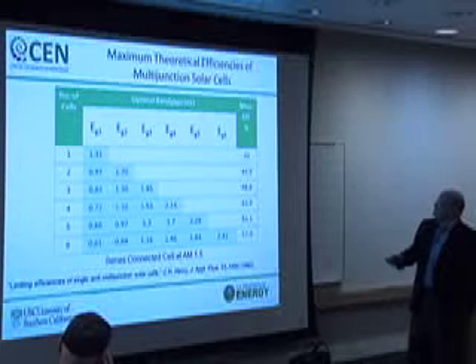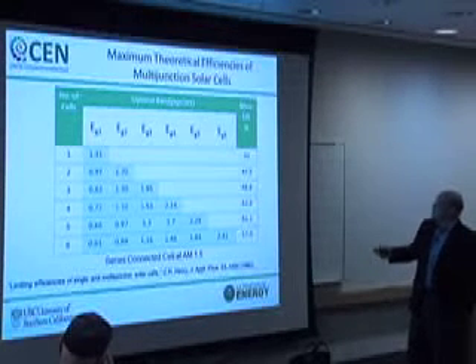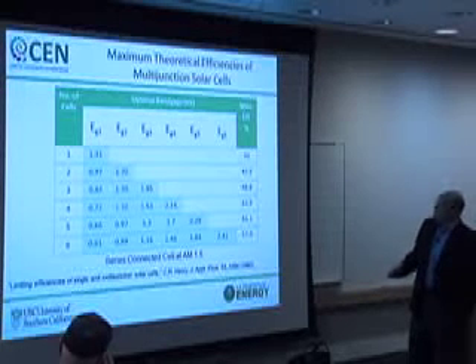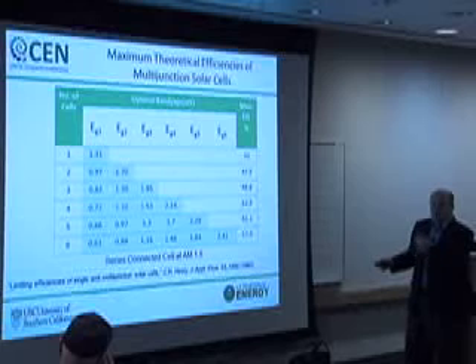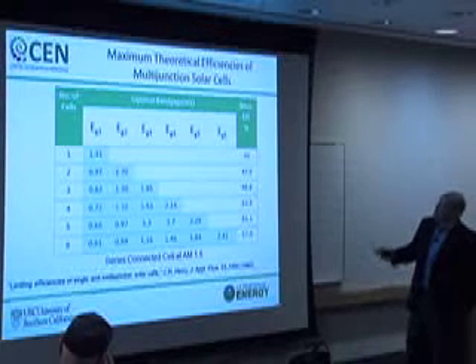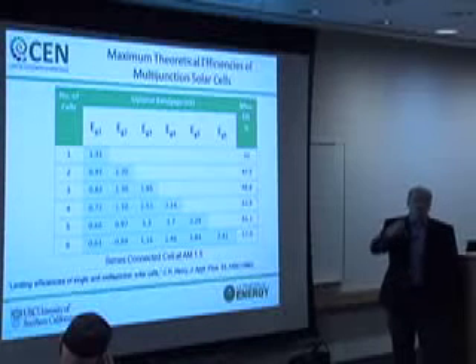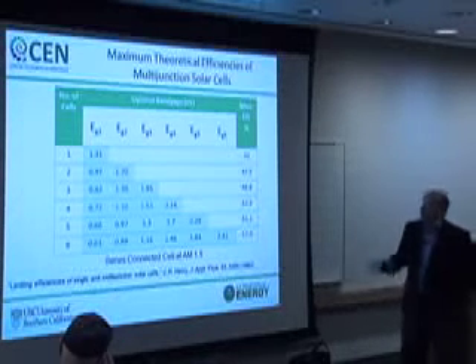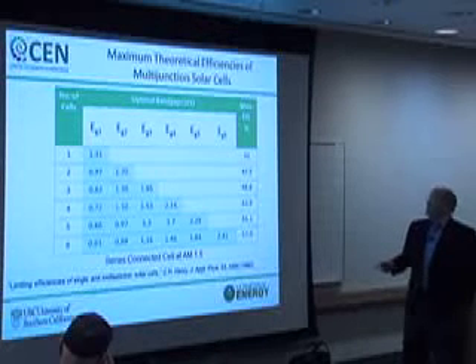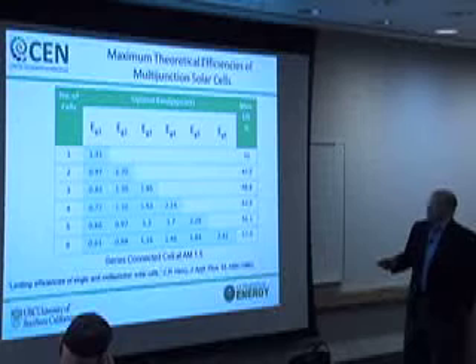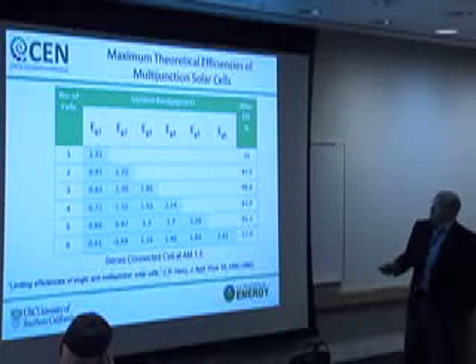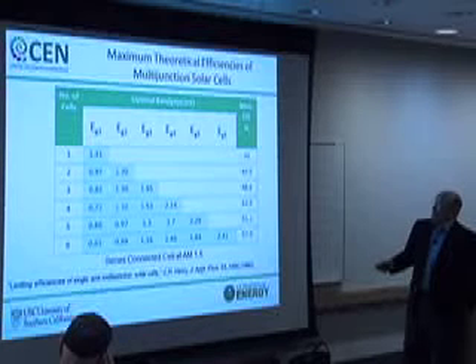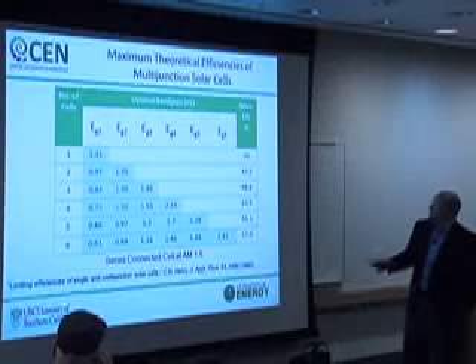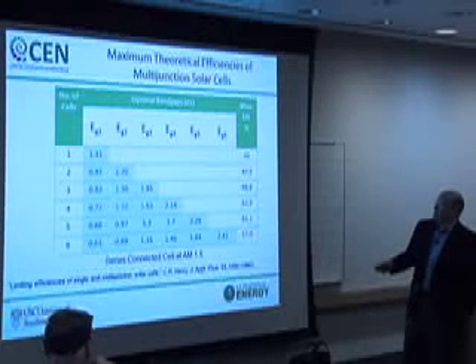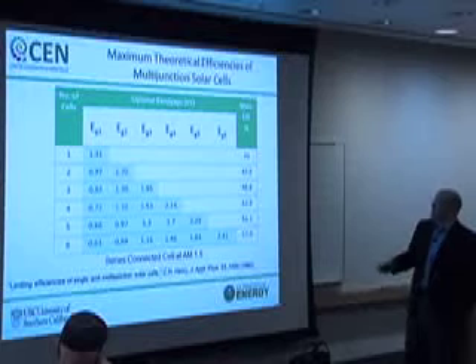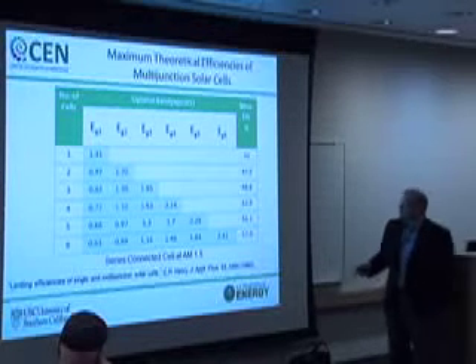what's shown here is the efficiency that you can achieve from this number of cells, in the same spirit as the Shockley-Queisser limit, and the band gaps that you need to use in order to properly segment the solar spectrum. And this is for an air mass 1.5. So for a single cell, it's well known that this is in the range of 1.3 eV. For 2 cells, you need one that's about 1 eV and 1.7 eV. For 3 cells, it breaks down as 0.8, 1.3, and near 2 eV, etc. And so you get the scheme here.